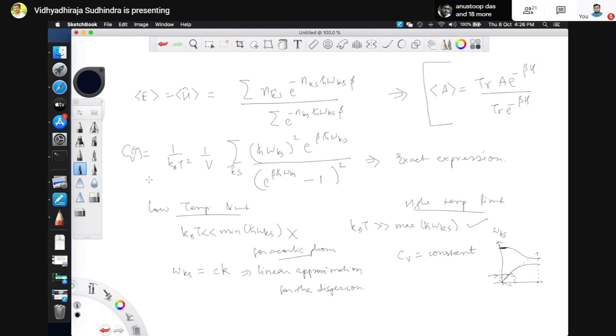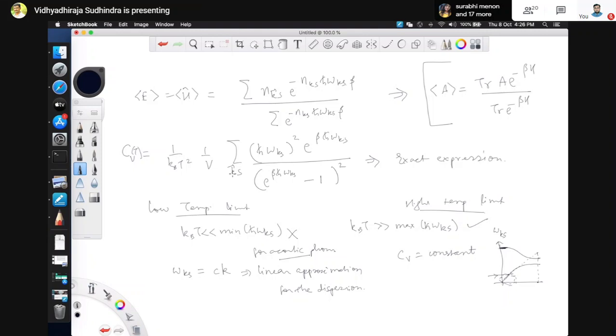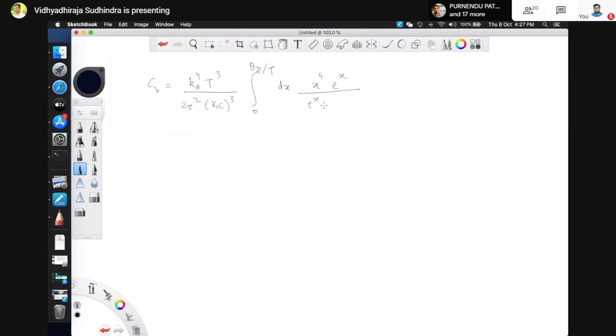Here also you can see that the specific heat is actually a sum over different branches. We are calculating the specific heat corresponding to the acoustic branch, and then you can consider the specific heat from the optical branch separately. For the acoustic branch we consider the dispersion to be linear, and with this linear dispersion we found an expression: CV = (kB⁴ T³)/(2π² (h-cross c)³) times the integral from 0 to theta_D/T of x⁴ e^x/(e^x - 1)² dx.